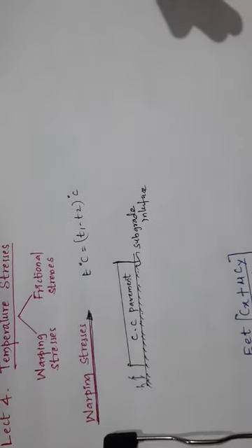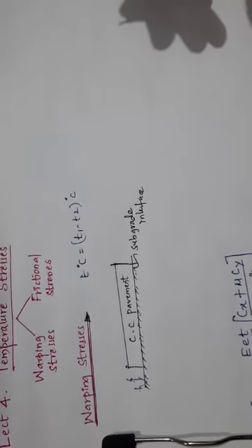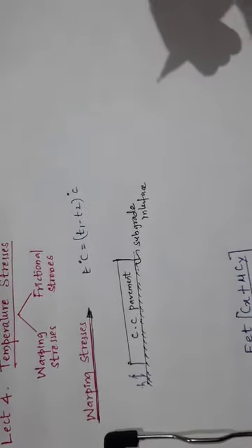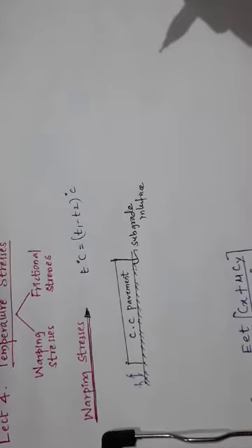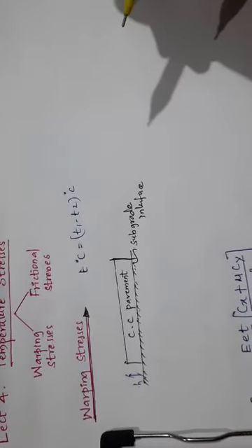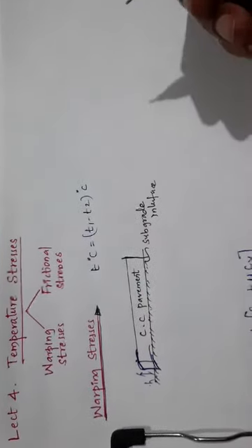during the warp, which causes it to warp or bend, as we call it. As the warp is resisted by the self weight of the concrete pavement, flexural stresses are developed at the bottom of the slab at the interior and the edge locations. At the corner of the pavement slab, the slab tends to warp downward. This is at midnight.